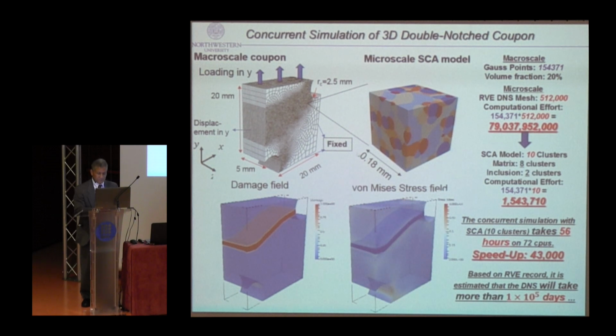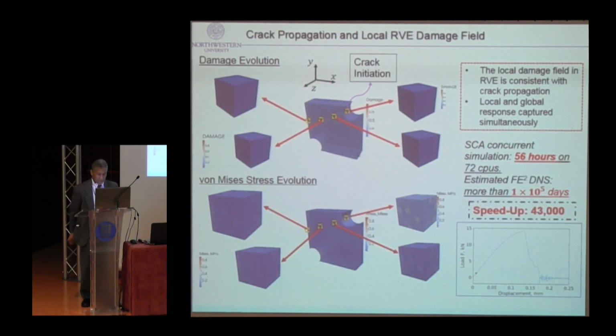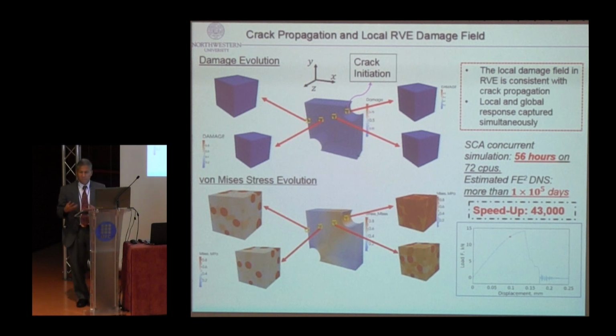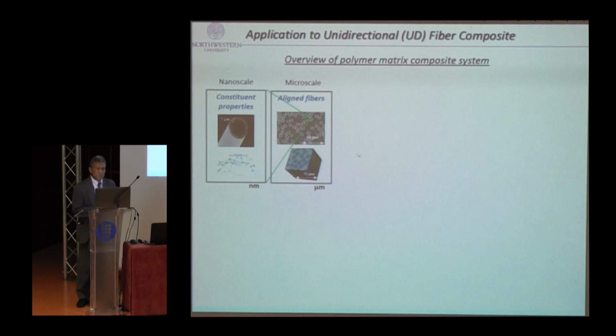And not only that, we can actually look at each Gauss point and how the microstructure evolves, because that is where we're interested, in the initiation of damage, so that we can design a material to minimize the damage in this case. You can look at the load deflection curve, at the same time look at damage, look at stress distribution, and that's where you can try to come up with a design of the microstructure on the fly. Now, we're working on another project on unidirectional fiber composite.